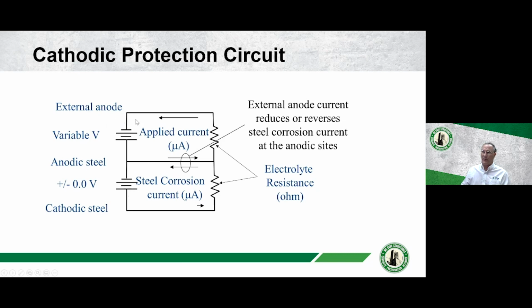The external anode, which is being supplied either a zinc, or magnesium or aluminum, or it's an external impressed current anode with a variable voltage, will throw current to the steel, and it will reverse the anodic corrosion current, so that it stops the corrosion reaction on the steel. The external anode has to produce more current than the native corrosion rate in order for it to stop the corrosion cell and polarize the reinforcing steel. Those are terms you're going to hear a little bit later on in the rest of the discussion.